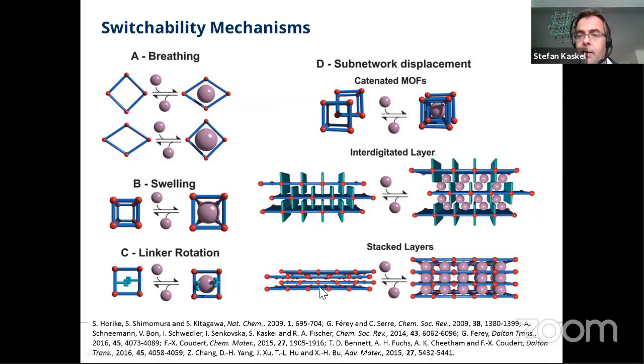We have here the stacked layer system that I just described, where the layers are separated from each other, similar to 2D structures. But nowadays we also know 3D structures that can show swelling behavior, or so-called breathing behavior. And in the breathing behavior, I will explain this in a minute, this is also a very typical case. We have a two-step transition from an open pore to a narrow pore form, and then again from a narrow pore form to an open pore form with increasing amount of gas. But there are many types of flexibility or switchability mechanisms that are recognized today. And this also gives us a lot of methods to tune this type of flexibility and pore size adaptability in a way.